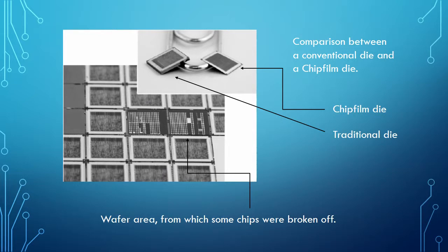Now this is a really interesting image. It shows the wafer area from which some chips were broken off. The dark area in the middle shows where the chips were. In the inset, a conventional die and a chip film die are shown in comparison, and we can clearly see that the chip film die is a lot thinner than a conventional die.